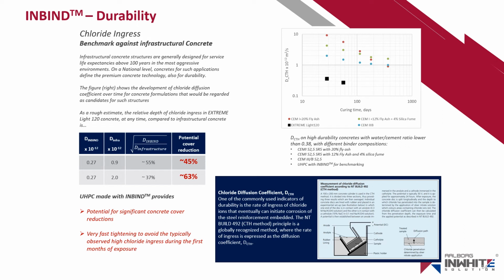What you're seeing here is a chloride ingress test according to a Nordic procedure, NT Build 492, or CTH method. In this method, the chloride diffusion coefficient is calculated. You can pause the presentation and read the test procedure explained in the blue box. These values that we got are linked to our product EXTREME Light 120, in which the binder used is InBind.